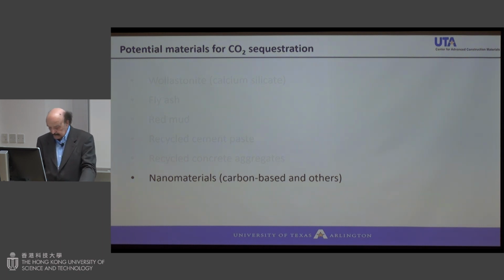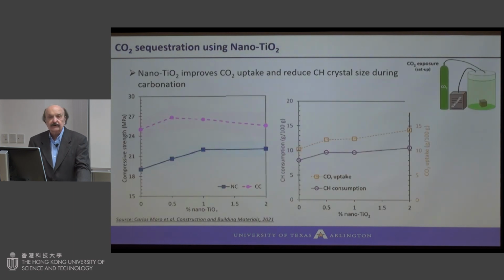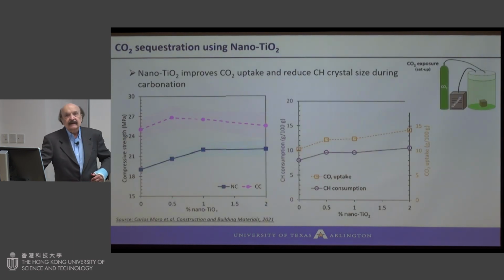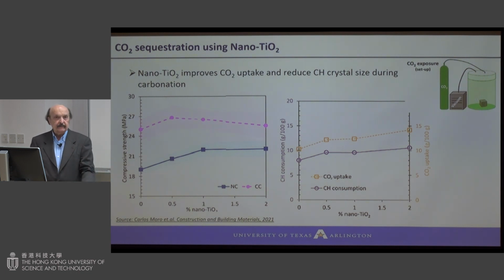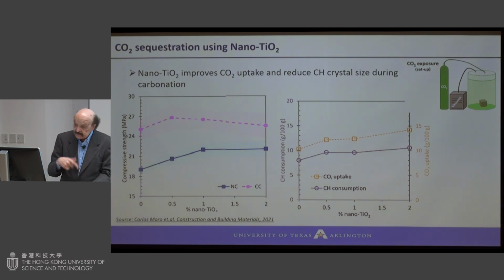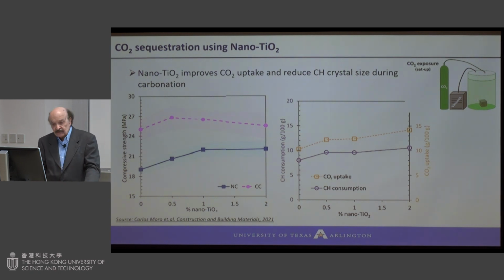So let's look. I was looking at a study done at Purdue University. They have been working with nano-titanium dioxide. Many of you know that we are using nano-titanium dioxide because of its photocatalytic activity. So you get a so-called self-cleaning surface, and it's available as an admixture. What they found was when they add from 0 to 2% nano-titanium dioxide to cement and carbonate it, then